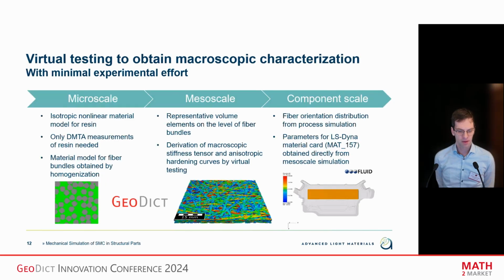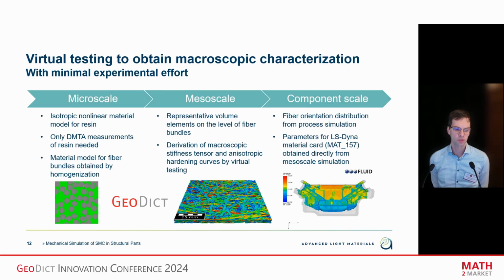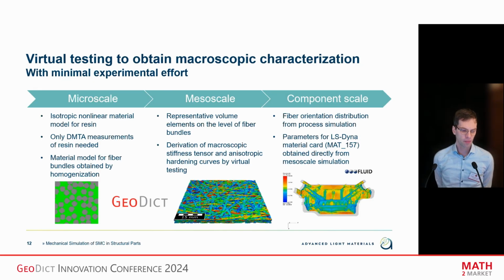So how to model this? As I said, we wanted to obtain a material card in LS-Dyna, which can reproduce this behavior using a 3-scale modeling approach. And another point where we put a lot of effort in is to keep the experimental effort as low as possible. So we start on the micro scale inside the fiber bundles, where we assume isotropic nonlinear material behavior for the resin, which can be characterized by DMTA measurements. And for the fibers, we assume linear elastic behavior, and then we obtain a material model for the fiber bundles by homogenization.